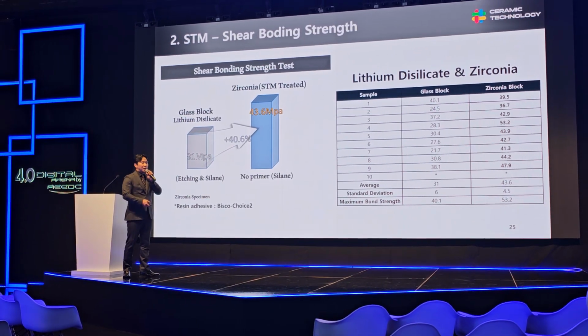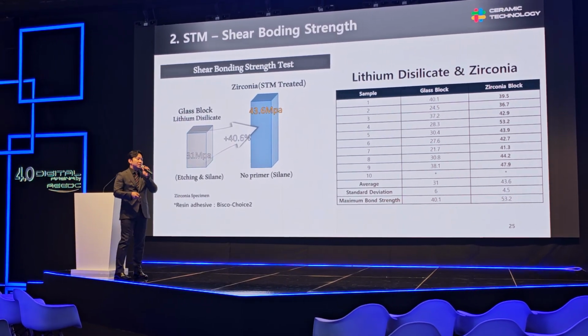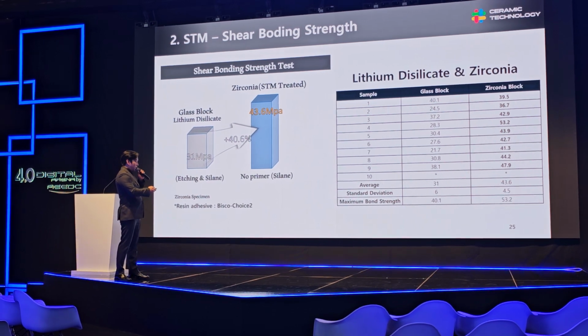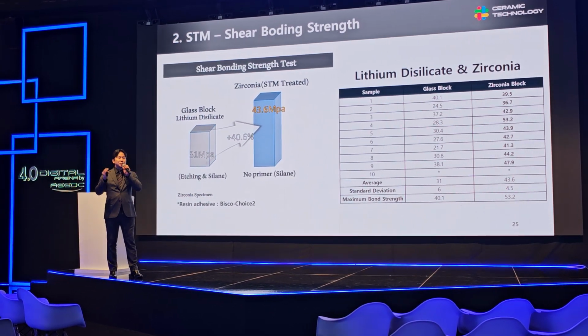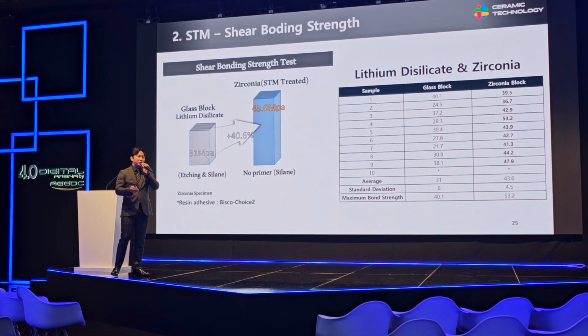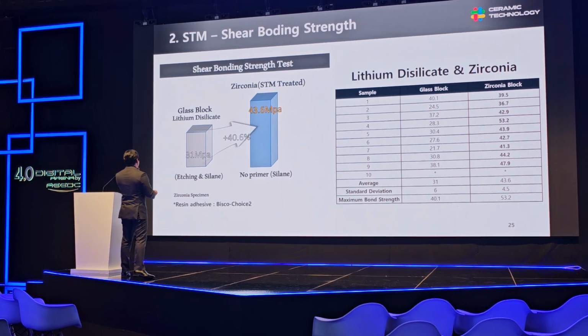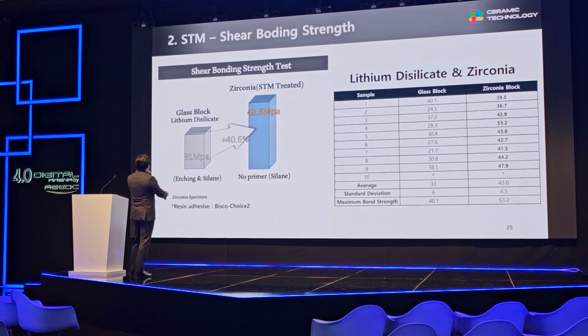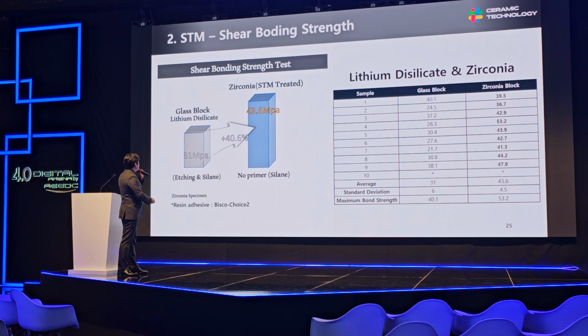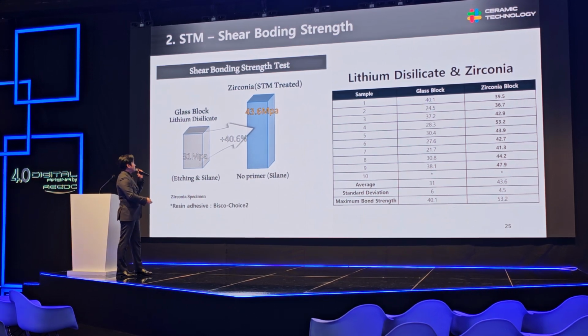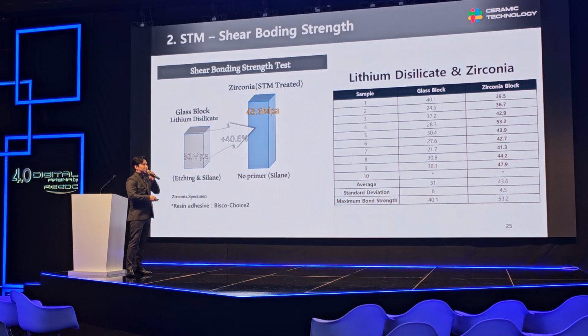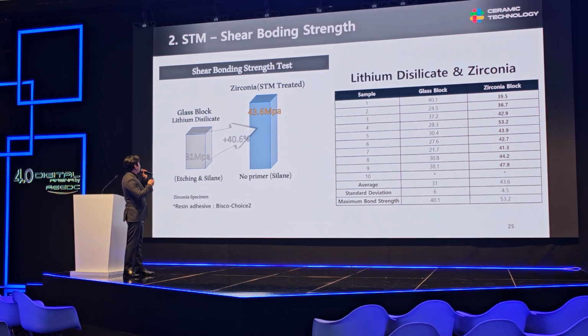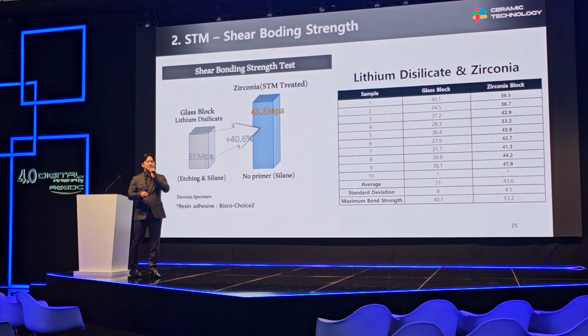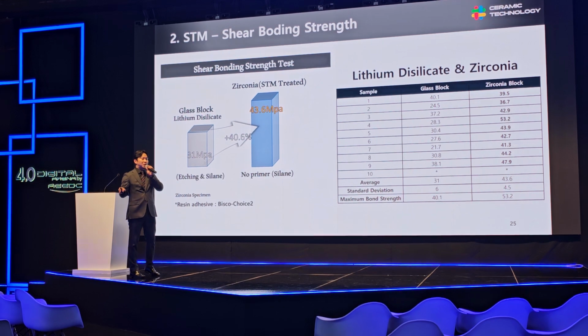And so, how much has the bonding strength improved? We know glass block has the highest bonding strength among prosthetic materials. So in the test, the glass block showed 31 megapascals, but STM-treated zirconia showed 40.6% higher than the glass block without primer.